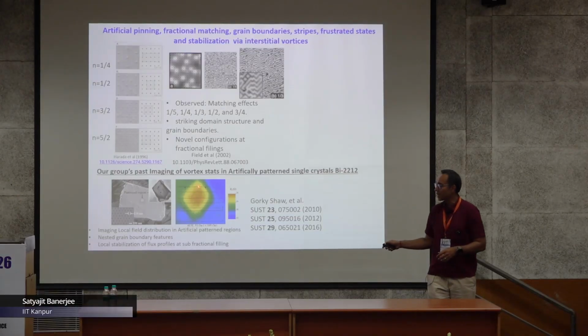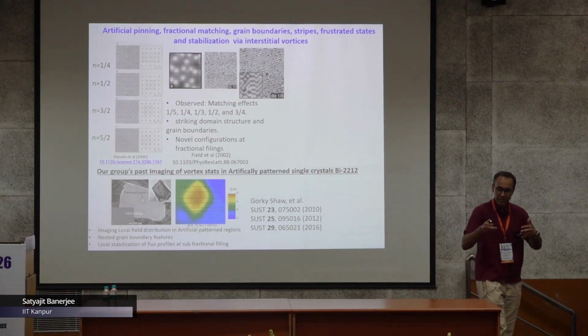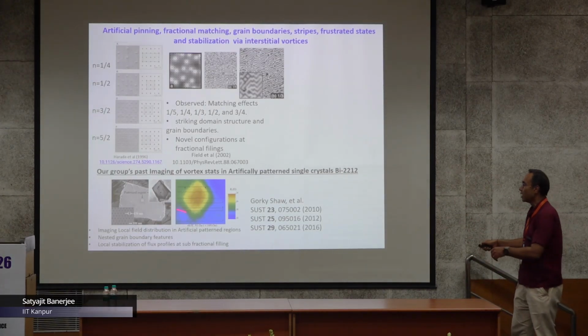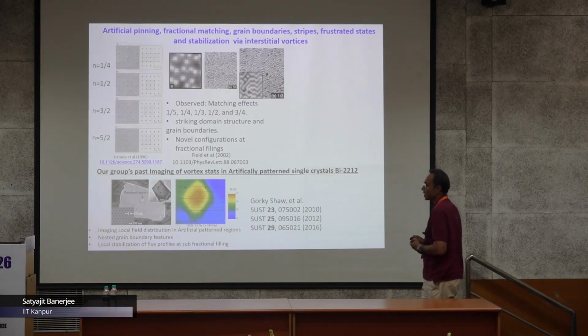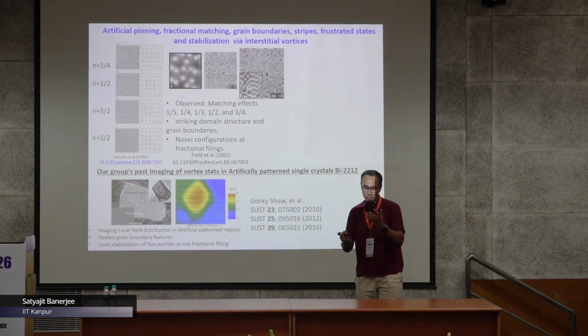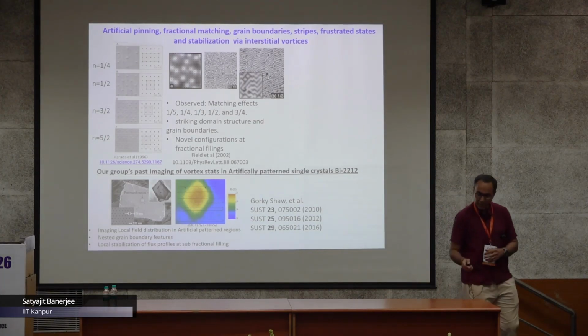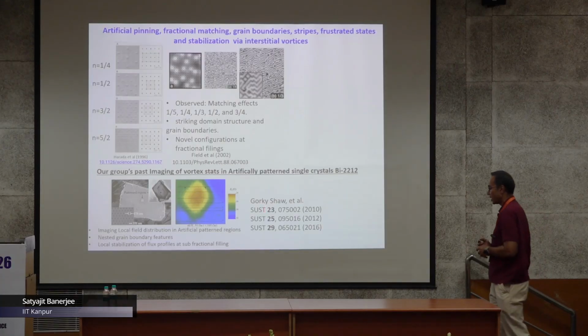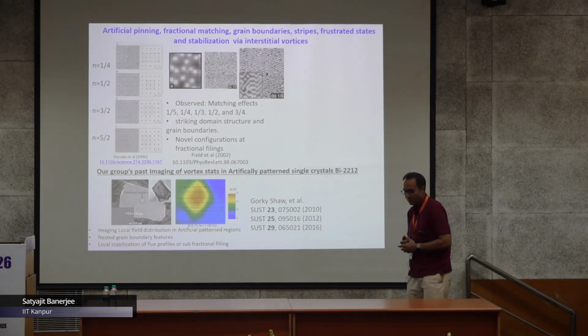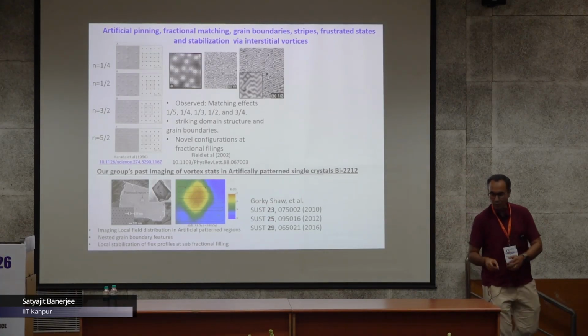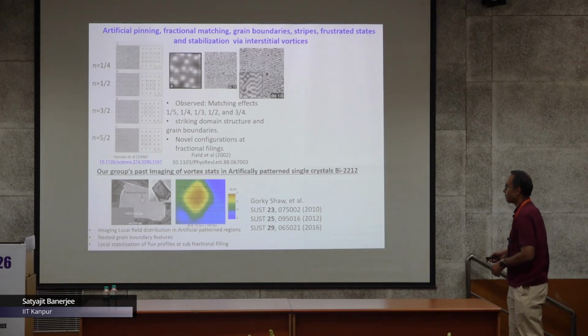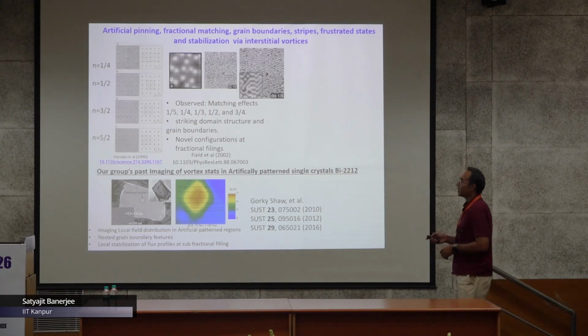And we could see interesting geometries of flux distributions present at these fractional fillings. There are multiple fractional fillings actually present, not only one, and we could control the flux structures. Mainly from an application point of view, we were looking at how to control the local flux distribution inside microscopic regions inside the superconductor. So this was way back in the past.